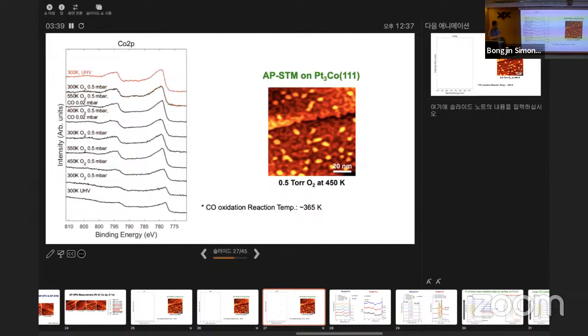And then again, when you introduce the CO, you start to see reactions of some of it. But as you can see, this is not fully going back to the metallic state. It still has broad features, which means it is maintaining this cobalt oxide state.